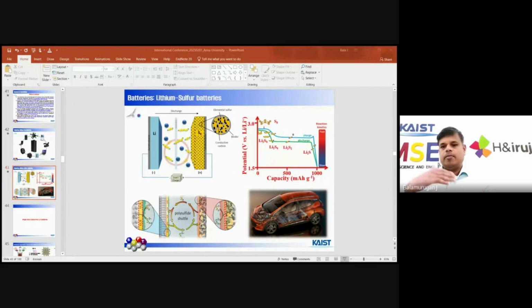Therefore, the sluggish kinetics are overcome by our newly developed materials, that material called cathode material. That cathode material may avoid the polysulfide shuttle effects. Then we can get higher performance for the lithium-sulfur battery using low-cost materials like a sulfur-based catalyst.